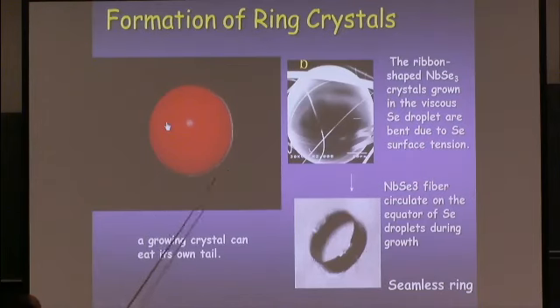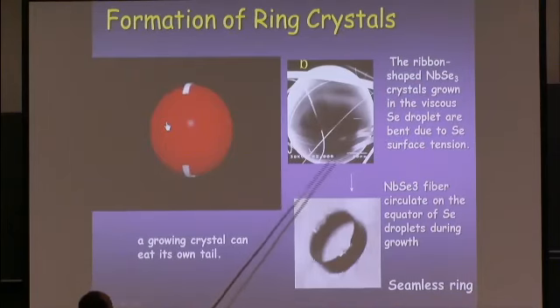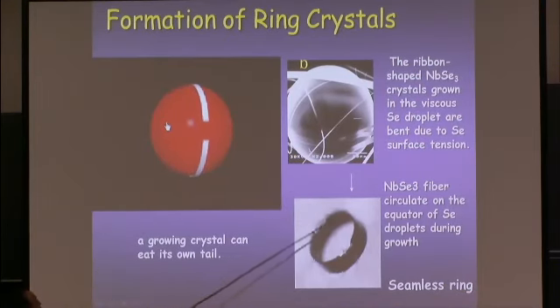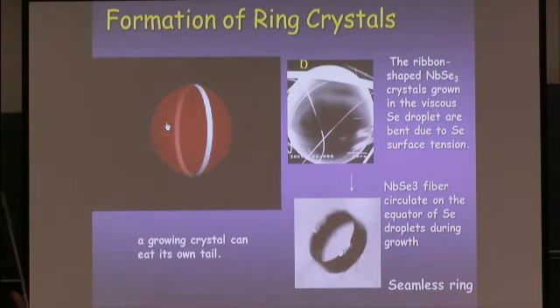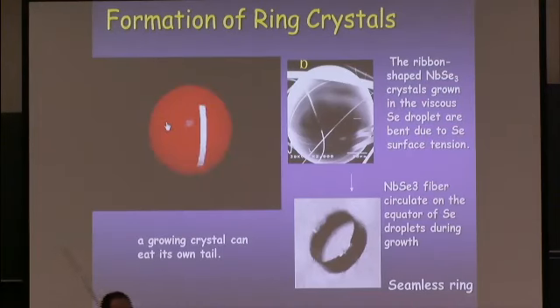The ribbon-shaped niobium selenium crystals grow in the viscous selenium droplets and are bent due to selenium surface tension. The NbSe3 fiber circulates on the equator of the selenium droplet during growth. A growing crystal can eat its own tail. And finally, the selenium evaporates. We can get a seamless ring like this figure.